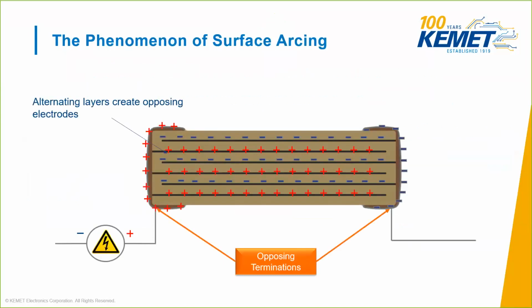Now, when voltage is applied to an MLCC, a potential difference is established between the opposing termination and opposing electrode structure. Because there are alternating layers of electrodes within the MLCC structure, there will be opposing electric polarities between each electrode. In this slide, we've shown the opposing termination and electrode polarities with red positive and blue negative signs. This opposing polarity produces an electric field between each electrode layer.